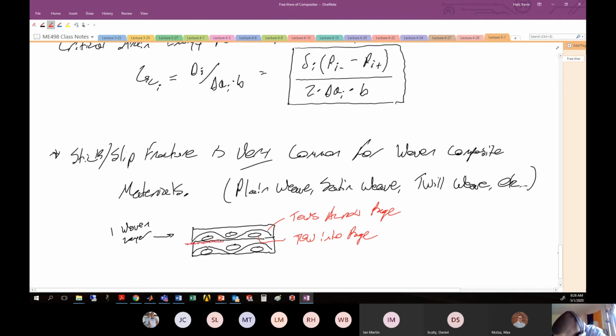the crack's going to propagate until it hits this rounded edge of the fabric. So hopefully we see this rounded edge and it gets pinned there. The crack will propagate, hit this rounded edge and stop. And then it loads, and then finally I can overcome this hump that is this woven layer.